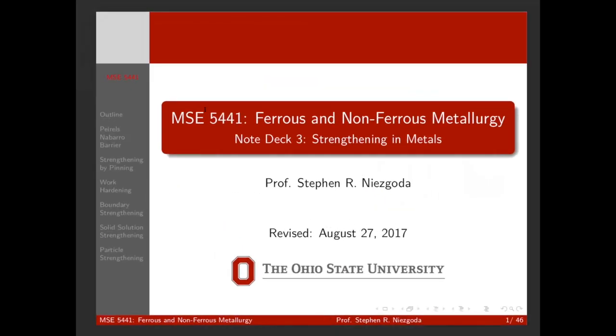So in terms of strengthening, what are the only things we can do? What is our total toolbox for making metals stronger? We're trying to increase the number of times our dislocations hit obstacles. So what obstacles do we have to play with? Solid solution strengthening, we can put in more solute. We can put in second phase particles. We can put in more dislocations, or we can make the grain smaller and effectively put in more grain boundaries. That's it. We've got 4 knobs we can turn.